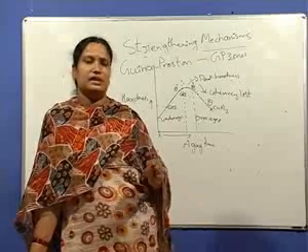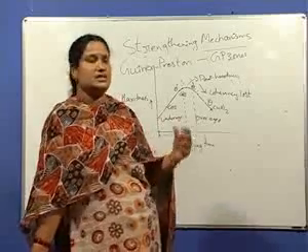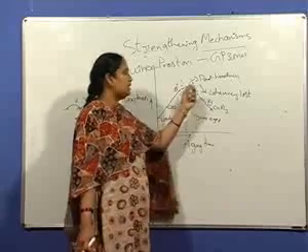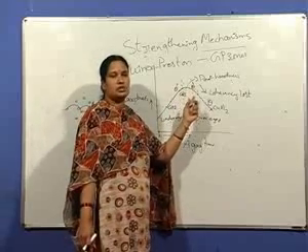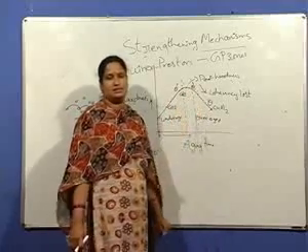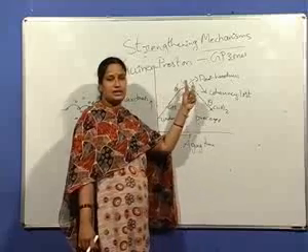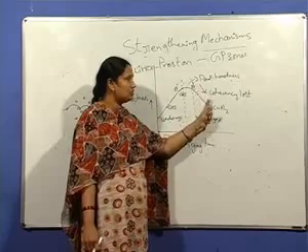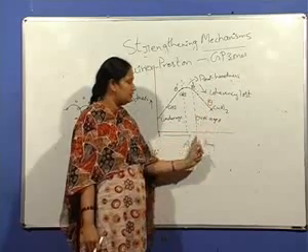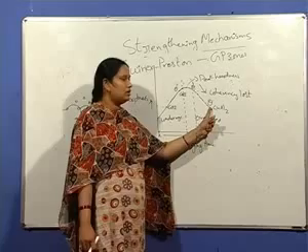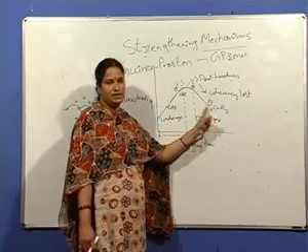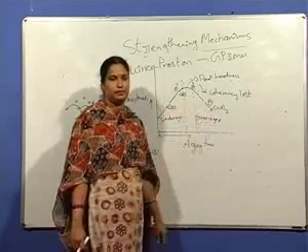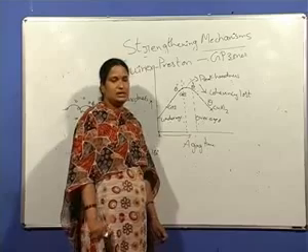With still further increase in aging time, these clusters grow in size and form theta prime, which is coherent with the matrix, whereby the hardness increases to the peak hardness, and finally the coherency is lost with further increase in time, the equilibrium theta phase forms, and coarsening of the precipitate takes place.